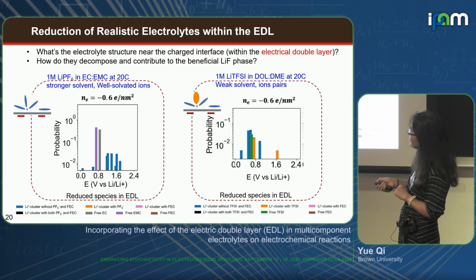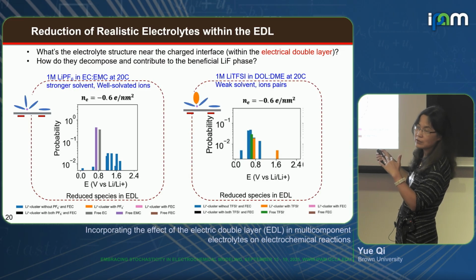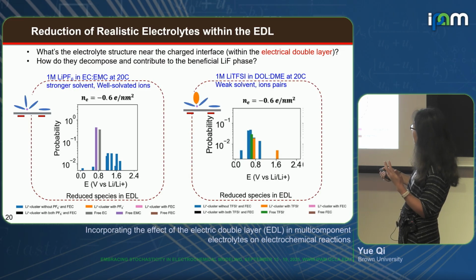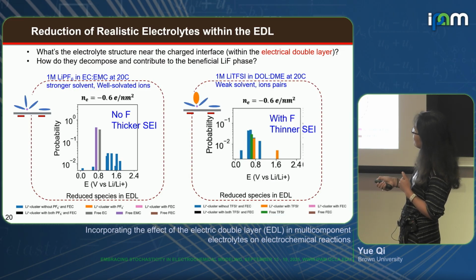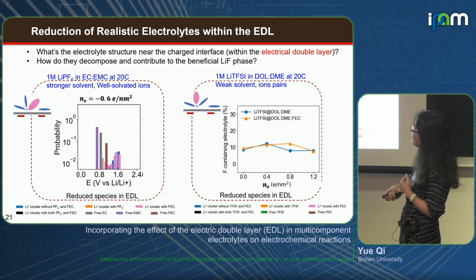The other thing is the solvent itself, right? The EC solvent themselves will decompose right here. These two solvents will not decompose as a free solvent, but if they're bonded with lithium, they will get reduced. All right. So overall, we have more electrolyte reduction for this one, but much less in this one.